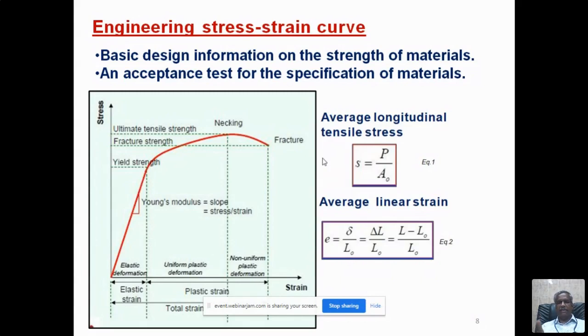As I told you, the gauge length should be marked before testing the specimen. How will you mark? You can use a marker pen. Suppose you are planning to have a gauge length of 50 millimeter. Find the center of the specimen in the length direction, and from the center you take 25 mm on this side and 25 mm on that side. You make a mark using a marker pen on the specimen. So that is the gauge length, and the gauge length is known. Then after testing, after failure, you keep the specimen together and you measure the change in the gauge length.